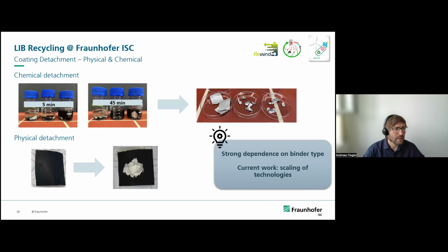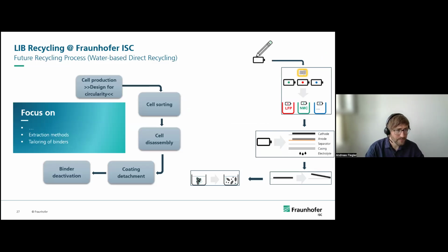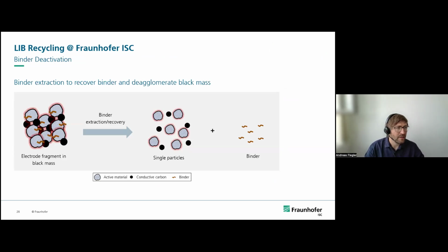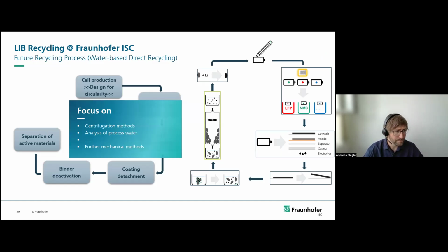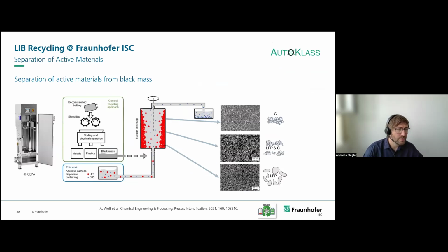And then we also work on different chemical and physical detachments. Here we use different solvents with different temperatures. And for the physical method, we also use some different approaches, for which the results are not published yet. So I cannot go into detail, but we see there is a very strong dependence on the binder type, and we also work on the scaling of these technologies. Then the binder extraction, I don't want to go into detail, but I want to say also, like Emma said, that it's a key topic to extract or deactivate the binder, so that we have single particles to go further with in further processes.